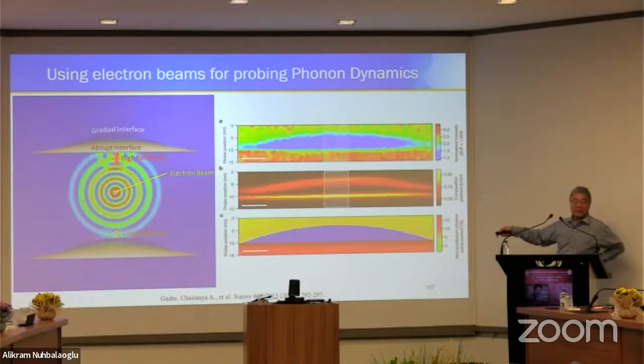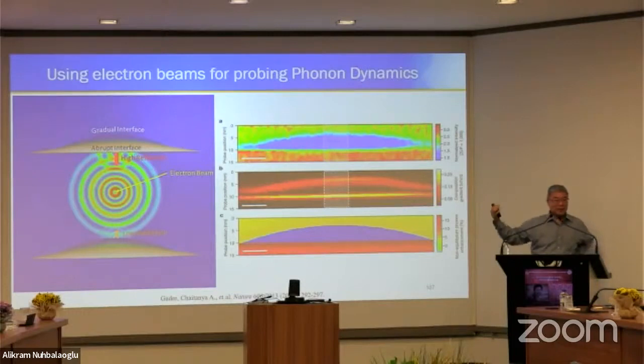It's more of a diffuse reflection. Therefore, some phonons still reflect, but to a lesser extent. Therefore, the phonon population here will be higher than the background. Here also much higher than the background. Therefore, this explains why we have two different enhancements. In other words, phonons will be scattered by the interface depending on the sharpness and composition of the interface. Okay, this was a good idea.